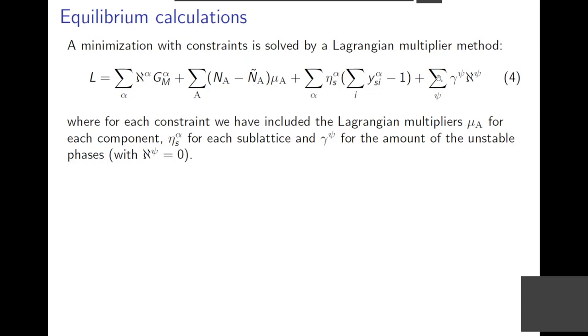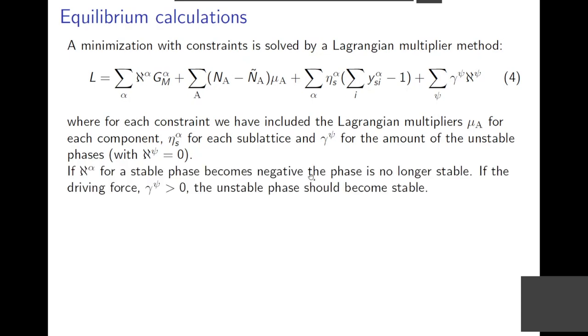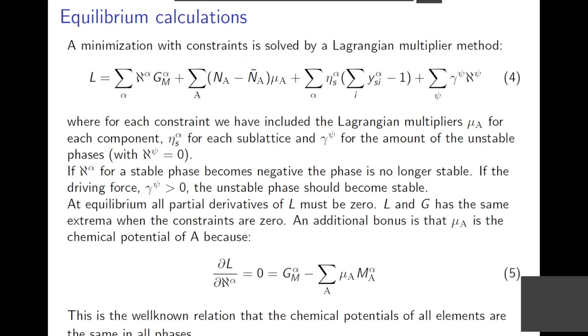And when you calculate diagrams, you normally need to be able to change the set of stable phases during the minimization, because you may start with a guess of stable phases, but your guess may not be so good. So if the amount of a phase here becomes negative, it means this phase actually shouldn't be stable. And if the driving force for this phase becomes positive, it means that this phase should be included in your minimization for the system. So that is automatically taken care of by the algorithm. And the chemical potential here is actually a Lagrangian multiplier. But it actually turns out to be the chemical potential of the system. So that also comes out naturally from the minimization.